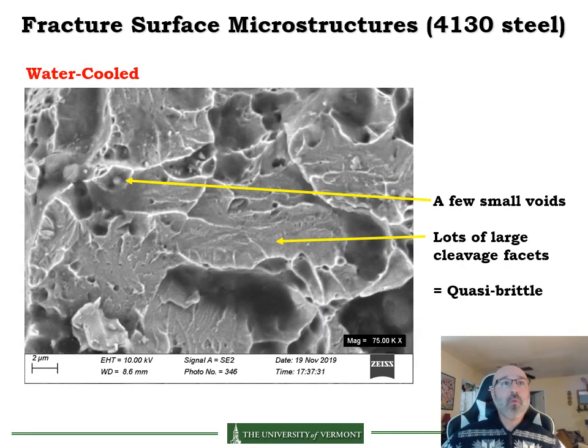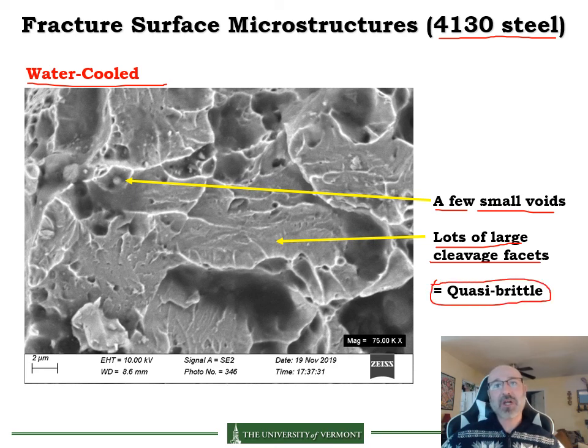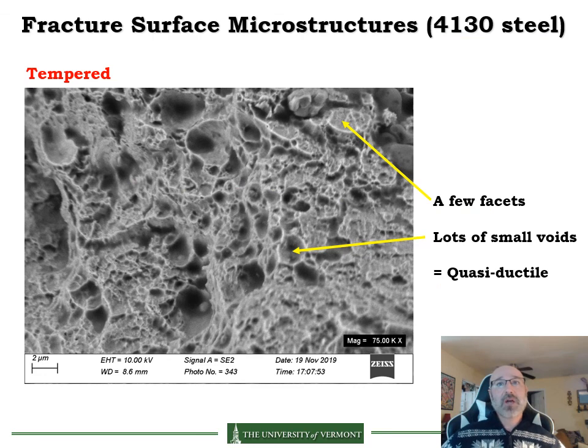Now we'll move on to a water-cooled 4130 steel sample under the scanning electron microscope. There are a few small voids over here, but lots of large cleavage facets. This is what we're going to call a quasi-brittle material, because you are still seeing some of those smaller voids, but it's leaning a lot more towards the brittle side with these large cleavage facets. Lastly, we're going to take a look at our 4130 steel that's been tempered. There are a few facets and lots of small voids, so we're going to call this quasi-ductile. It has some of the properties of being a little bit more brittle, but it's really leaning toward the ductile side by looking at all the structure here under the scanning electron microscope.